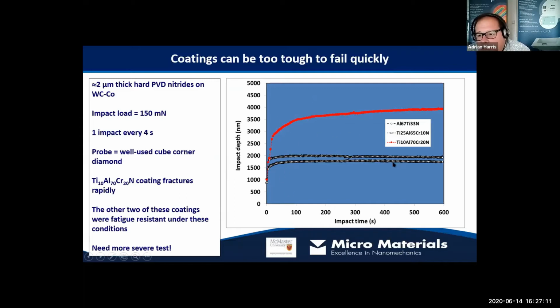We've got 3 coatings here, 2 titanium aluminium chrome nitrides. So just consider these guys. One of these titanium aluminium chrome nitrides has failed very quickly. So this is time. This is a 10-minute test. There's one impact every 4 seconds. So in this test, there are 150 individual impact events, and for each one, we measure the probe depth.